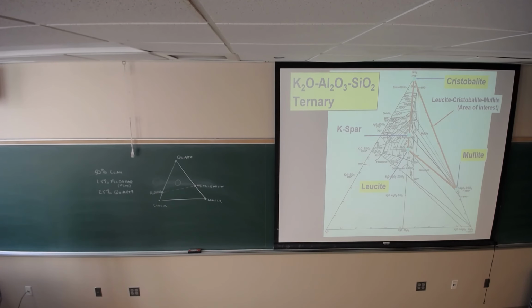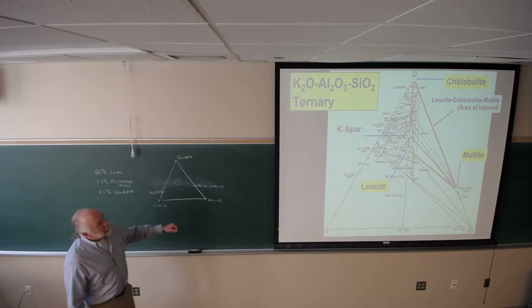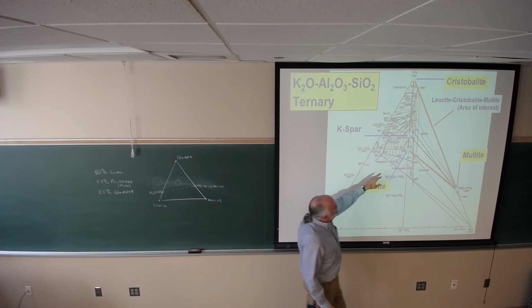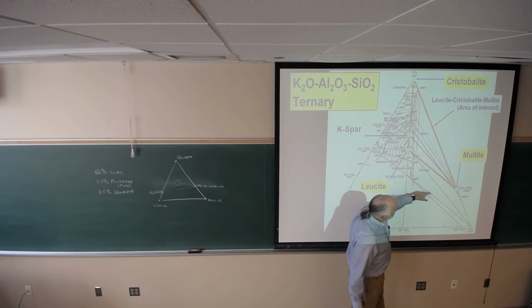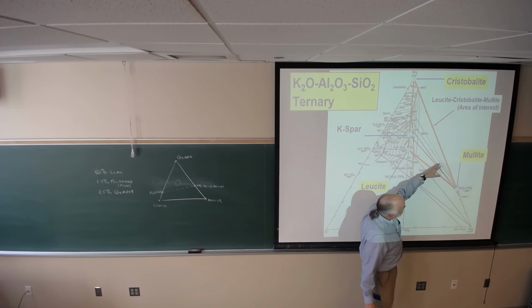So that means that these are equilibrium conditions. Fair enough? Okay? Which we don't usually see in reality, but it's a change in phase diagram. The red triangle you see here is actually what I replotted here. Okay, so here is leucite, here is potassium feldspar, here's mullite, and you notice that metakaolin isn't on the diagram.